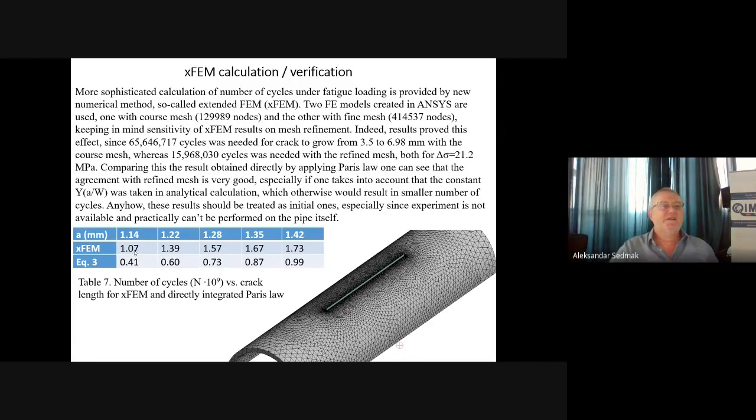And you can see here that XFEM provides about 2 or up to 2.5 times more life than the conservative analytical approach. That was something that we really expected because, as I told you, this analytical approach was too conservative.